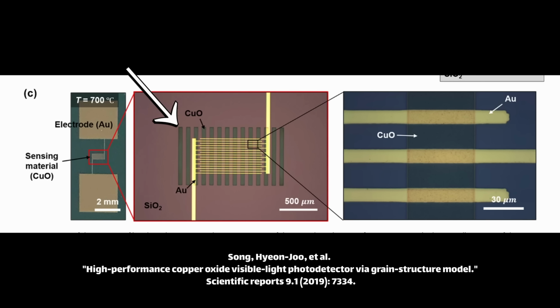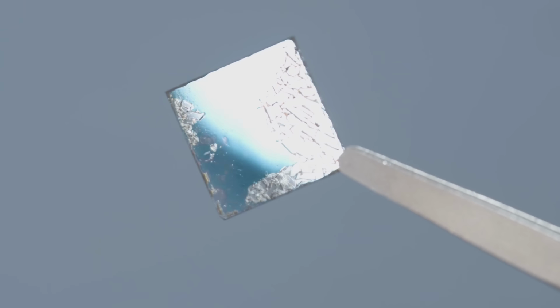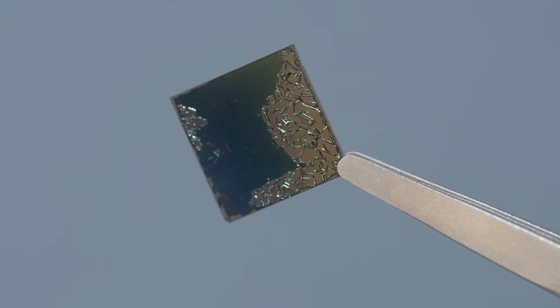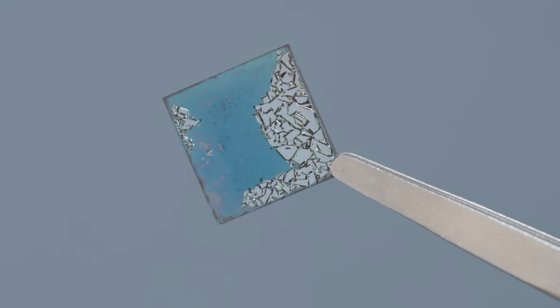Basically, they used thin, narrow strips of copper oxide instead of a continuous film because the smaller surface area has less internal stress, and so it's less likely to peel off. And I definitely found this to be a problem. If you have a single continuous film across the whole substrate, it's highly likely that it'll peel off, usually an hour or a day later. You actually get big flakes of the film just kind of coming right off. So it's totally unusable. Their method definitely works, having a smaller cross-section.